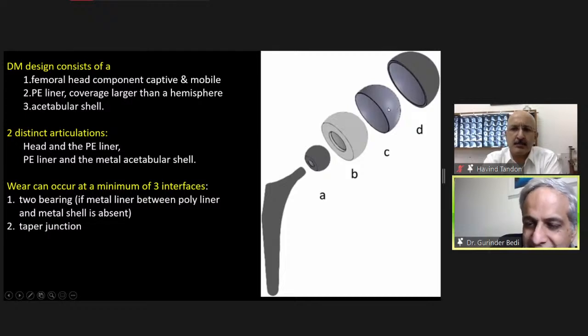So the intervening thing is something which was added on by the Americans. The French never had the intervening thing. They went with the idea that you will only have the shell and the plastic will move inside the shell. The problem is when you start adding screws, if you don't get a hold, then you need to add this metal inside. Remember, now the surfaces are very, very different. So you've got two dissimilar metals.